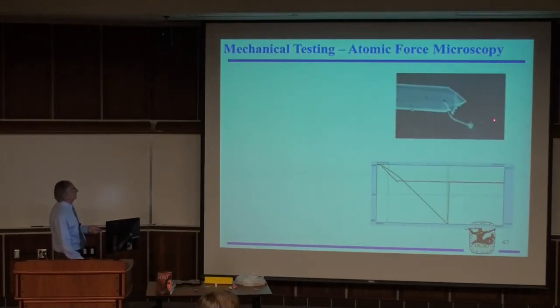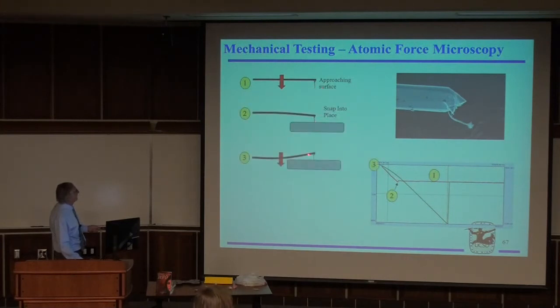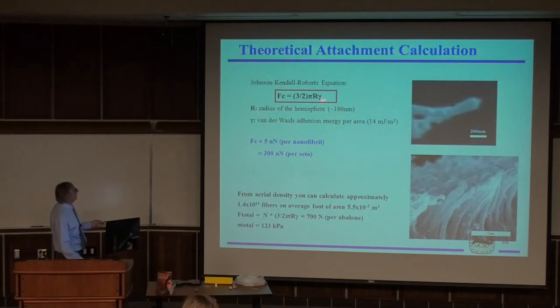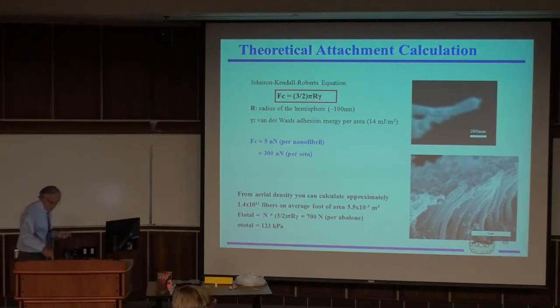I'm not going to go into the details, but here we have these tiny little fibrils. We put them in the AFM, we compress, and then pull in tension, and then it breaks apart here. We can calculate the force required. Like here, you approach the surface, it touches, van der Waals forces, you push a little bit, and then you pull, and when it comes apart, you measure this force. You apply an equation called Johnson, Kendall, and Roberts. These fellows from Cambridge looked at the van der Waals forces when you have a semi-spherical cap on a flat surface. They came up with this beautiful equation, and we find that each seta has a force of 300 nanonewtons.